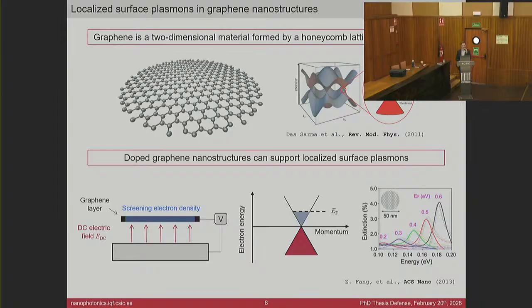Now, something interesting here is that, well, this is expressed in photon energy, but if you express it in wavelength, you can see that the resonance wavelength is approximately on the order of 10 microns, while the size of this nanostructure is of the order of 50 nanometers. And this is not going to help us to achieve lattice resonances.